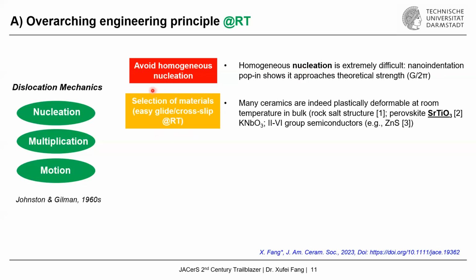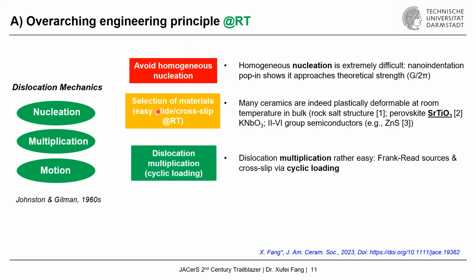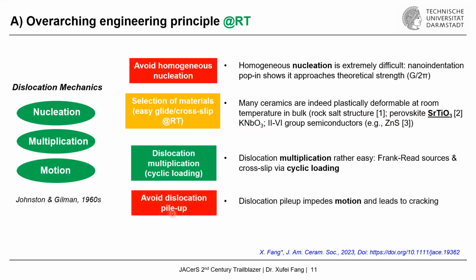And of course, the second thing is we need to select the materials, especially for room temperature deformation, in a smart way. That means we need to choose materials that already show some good ductility at room temperature, for example, the rock salt structures, sodium chloride, magnesium oxide, perovskites, strontium titanate, potassium niobate, and even zinc sulfide, etc. And once we have overcome these two components, the third part, dislocation multiplication, as will be shown later through cyclic loading, becomes rather easy. Again, as I mentioned just now, we need to avoid dislocation pile up, which would also lead to cracks. So I will give you some concrete examples of the homogeneous dislocation nucleation criterion, and also dislocation multiplication, by focusing on strontium titanate, which already shows very good room temperature dislocation mobility.